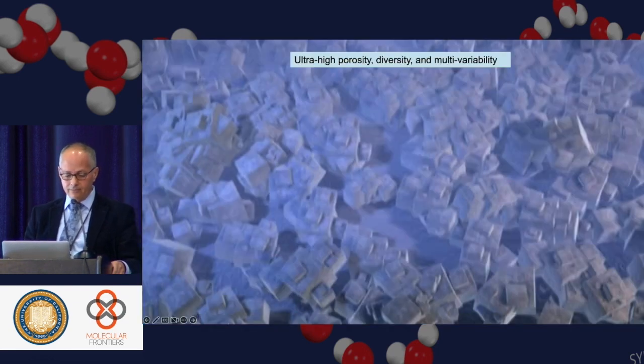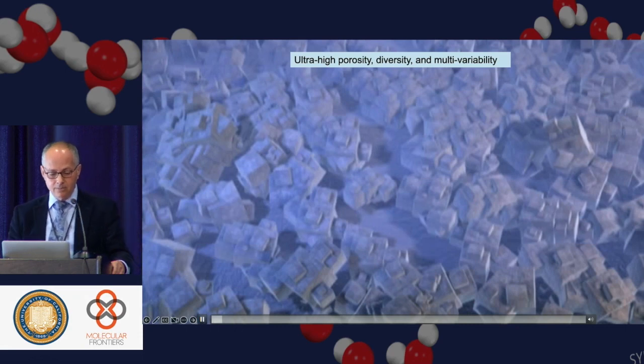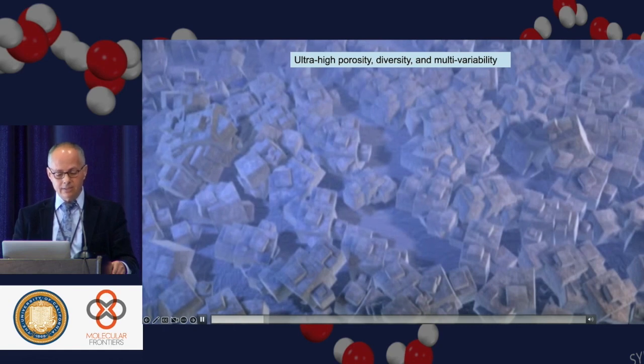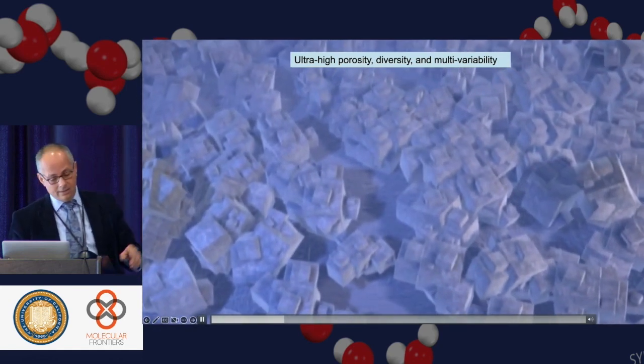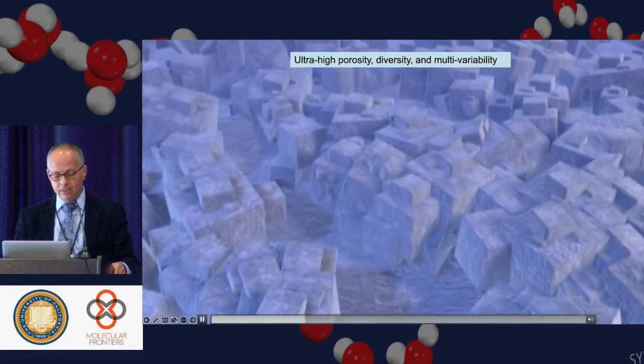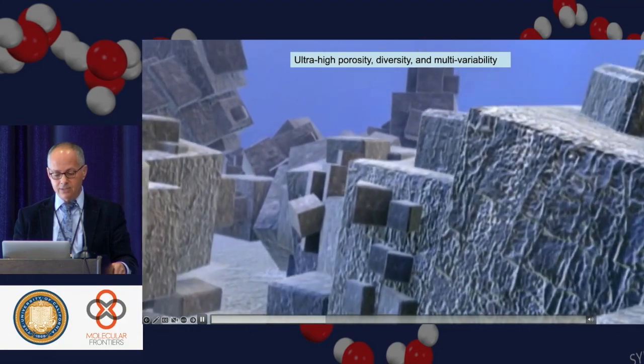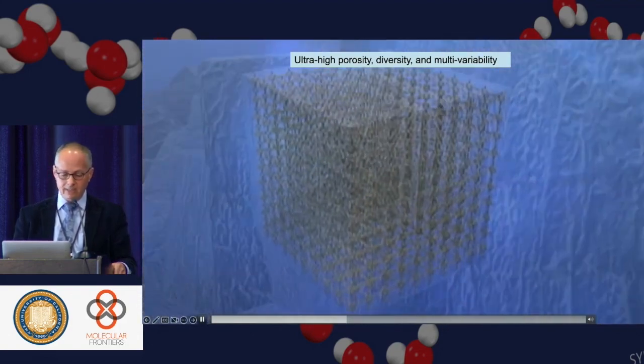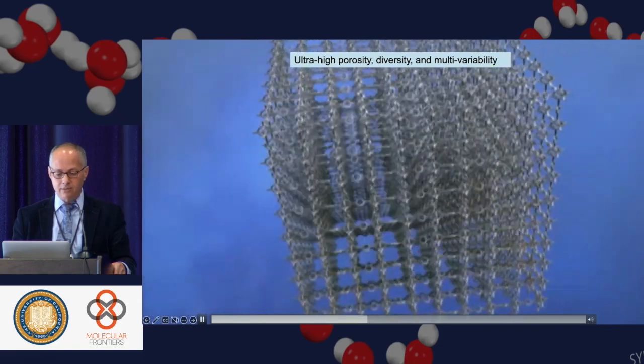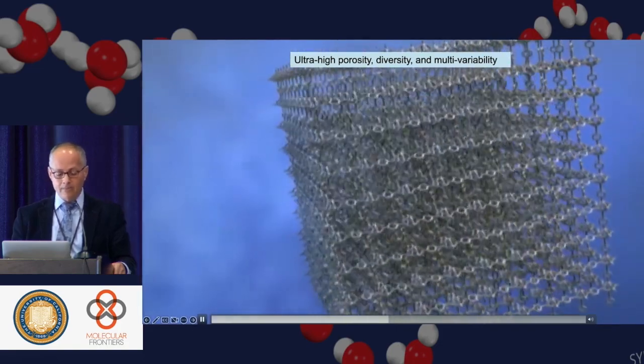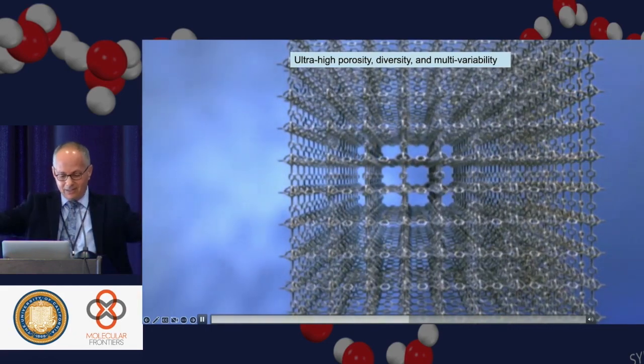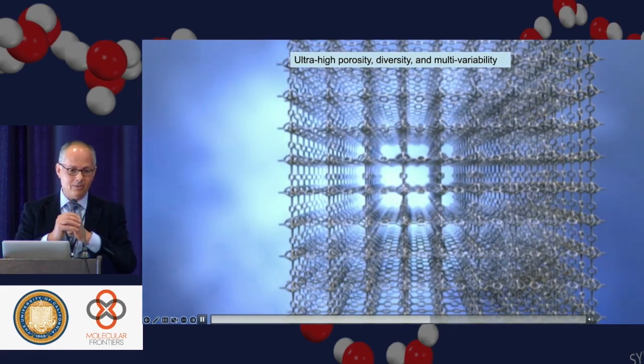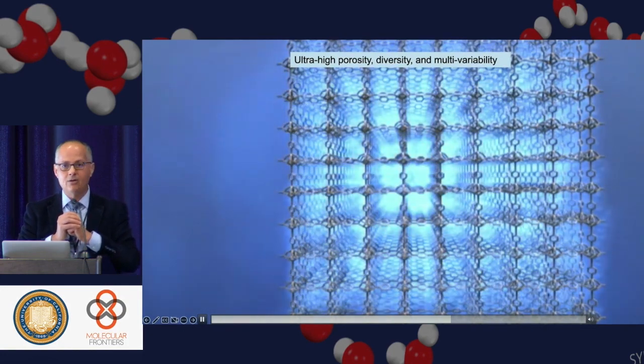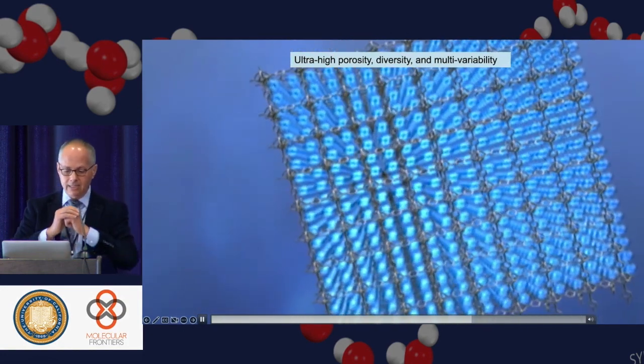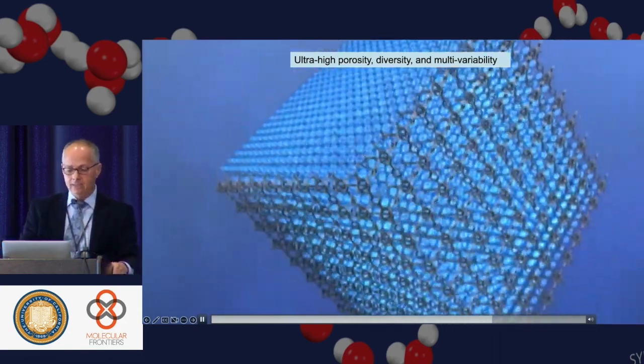So we have been able to make materials by stitching molecules together to make extended structures that are porous and that are crystalline. You can see here in this movie, you have crystals with sharp edges, faces, and you can characterize them by single crystal X-ray and know exactly what you have and how they're connected and all these structural parameters. They're very open. And the idea was that gases that fill very large volume could be compacted within the pores without having to use high pressure or very low temperature. So that now you can store gases in an efficient way.